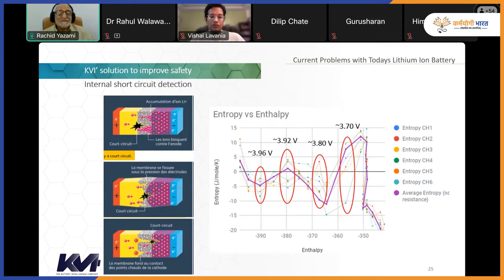So there is heat. The reason why a short circuit can appear is either the separator breaks somewhere, or there is some solid component, like some carbon materials, that can travel between anode and cathode and make a short circuit. And also during the fast charge of a lithium-ion battery or at low temperatures, the lithium, instead of being stored between the graphene layers, starts to grow as metallic lithium. And this metallic lithium is called a dendrite. It's a very tiny filament of metal, and that filament can grow and cross the separator and create a